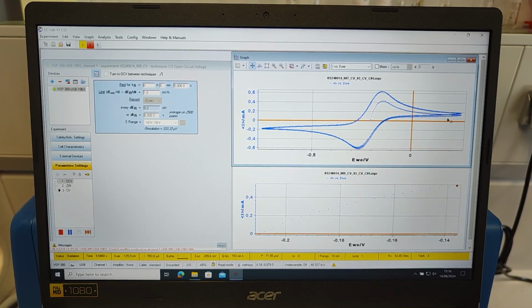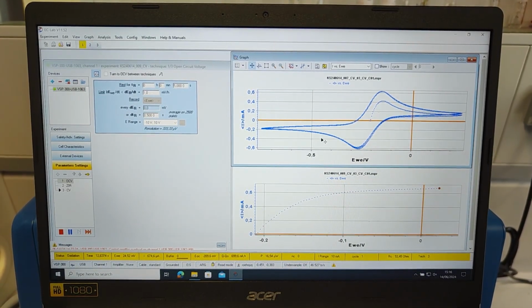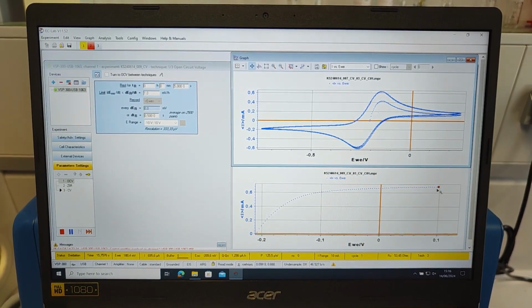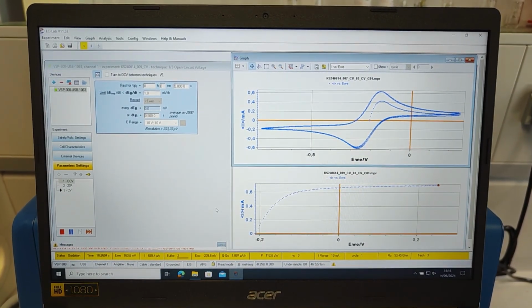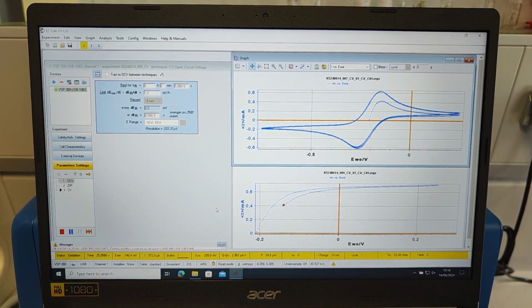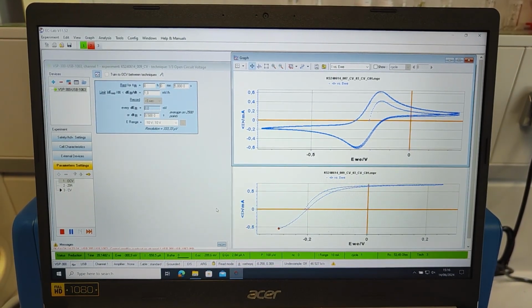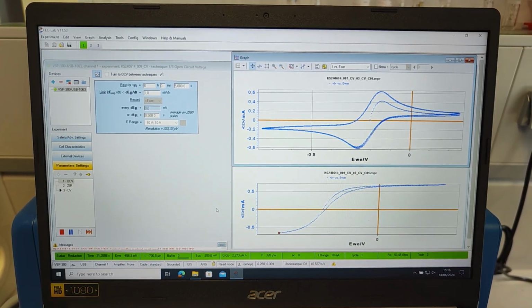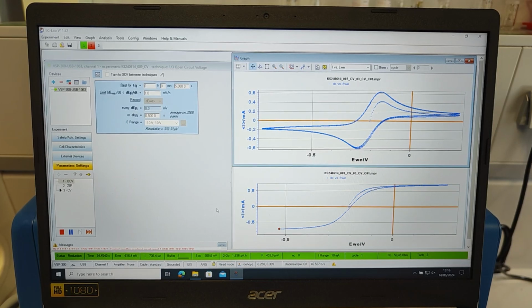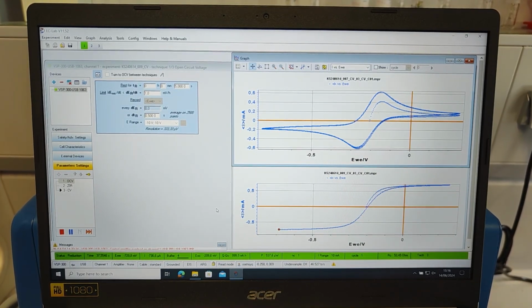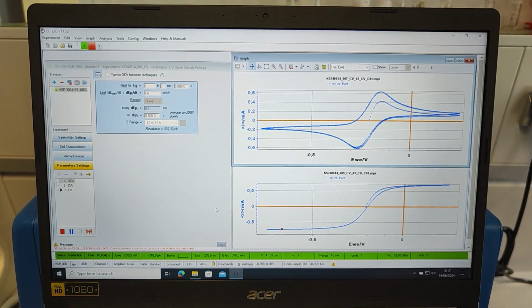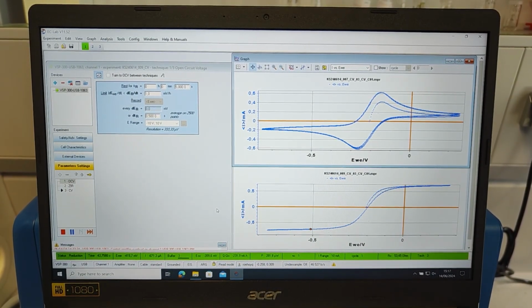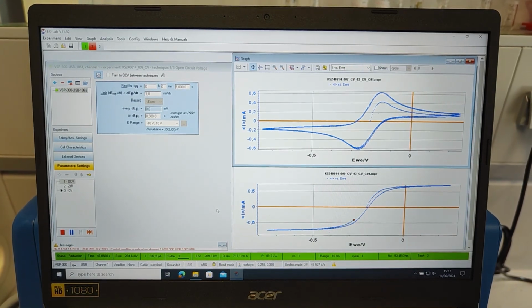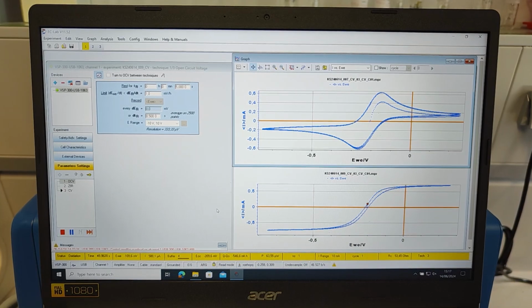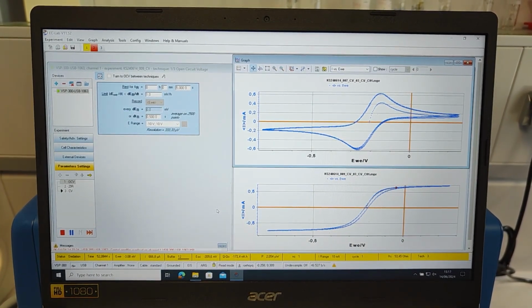Now here is the old CV on top without rotation, and now we can see the one with rotation is measured at the bottom, and we see we don't get a peak, more like a current plateau. Now we are going to the negative region, again getting a plateau, and together it gives us an S shape, or more professionally, a sigmoidal shape. So it's a bit different if we use this rotation or not. And now I will hand over to Sebastian, who will explain this behavior on the whiteboard.